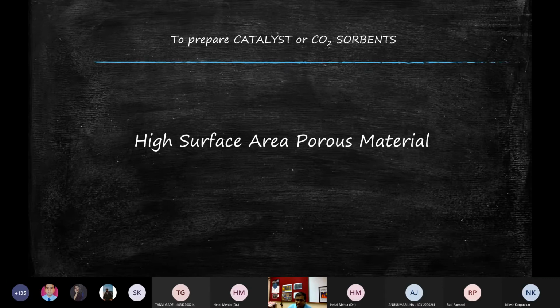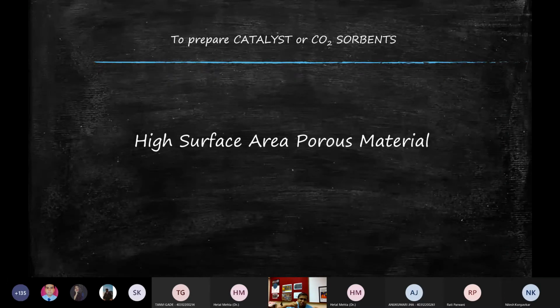Now CO2 is a bit acidic, so I make my surface basic, it's simple acid-base chemistry, and you capture all the CO2. And then if surface area is high, then your interaction of the CO2 molecule with the basic sites will be more, and you will be able to capture more and more CO2 faster and faster in terms of kinetics. And the same will be true in terms of catalysis, right? You will have a better diffusion, better interaction of the reactants with the active site, which is spread over the surface, and you will be able to do faster and more efficient catalysis.